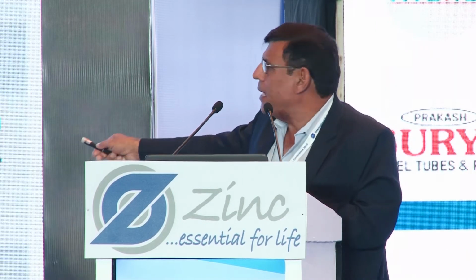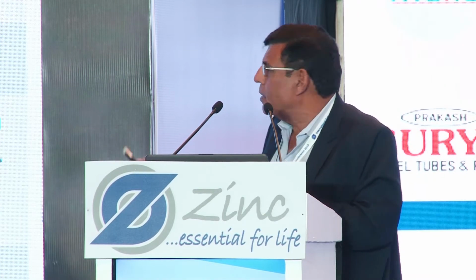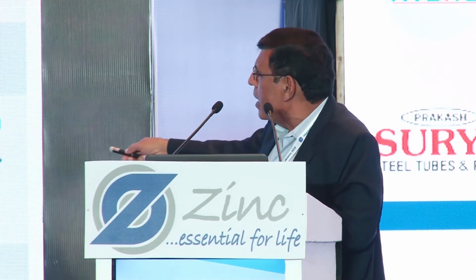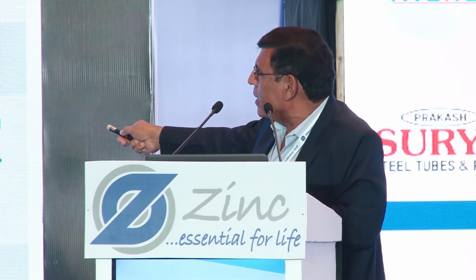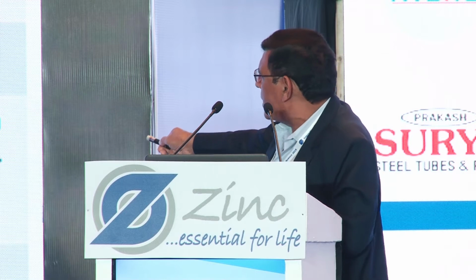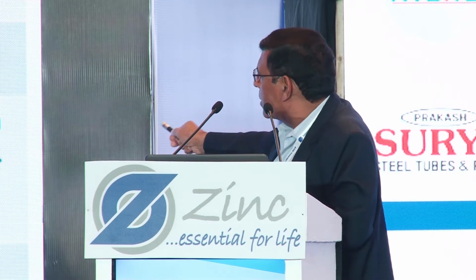Holidays and pinholes. Again, this is possible in case of organic coatings. This problem is again not there in the galvanized bar because it is a metallic coating. Then bond to concrete, very, very strong in this case. And only in the FBEC you find there is a 13% loss in the bond strength. Corrosion protection: black bar, very low. TMT, very similar to that. FBEC, very strong because it is a barrier coating. SS has a passive layer. While in the case of galvanized, you have barrier plus cathodic protection. And that makes it more useful.